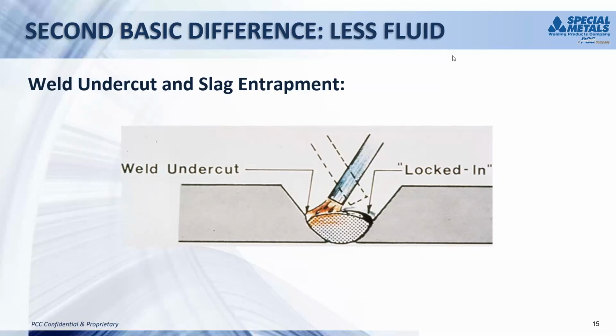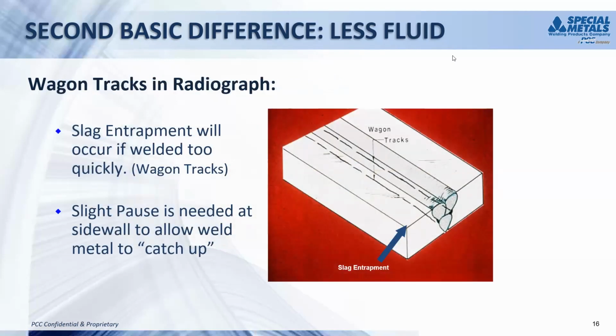And maybe some of you have experienced that in the live welding forums that we've had. We'd always ask, hold your hand up if you have had wagon tracks before. And it's amazing, probably 30 or 40% of the audience would admit to having wagon tracks in their first welds. John, if we can have the next slide. It's a picture of what is causing wagon tracks in your x-ray. The wagon tracks are those intermittent straight lines along each side of the weld, somewhere down in the weld. And if you notice at the end section there, there's the place where the slag trap is being caused. And so that's what happens if you weave too fast. So you need a slight pause, weld here and hold, weld here and hold, weld here and hold, and so forth, because of the puddle viscosity. Okay, John?